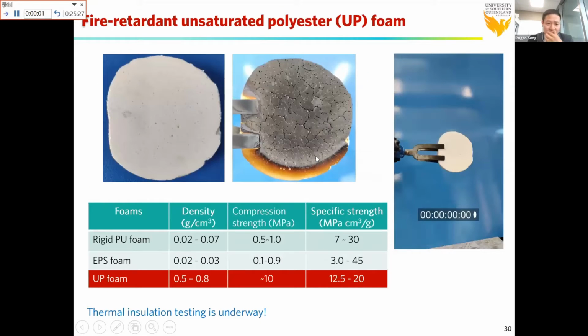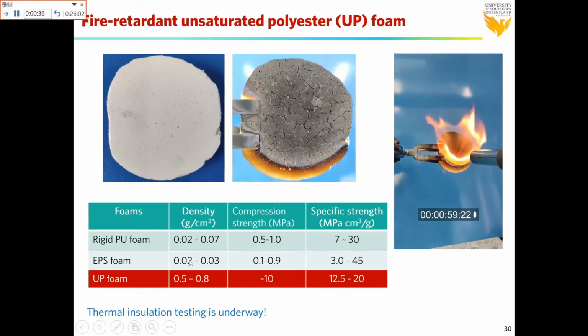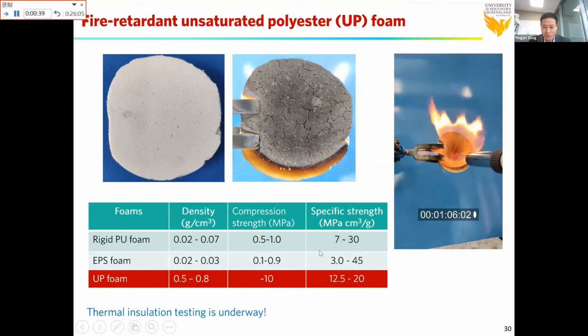So next, I'm going to share our recent work on flame retardant unsaturated polyester foam. This is just a microfoam in the laboratory. You can extinguish it in 1 second. If you ignite it, the fire is very small. On top of that, its strength is very high. Its compression strength is about 10 megapascal. It's much stronger than the rigid PU foam and EPS foam. Although its density is higher, we are evaluating its thermal conductivity.